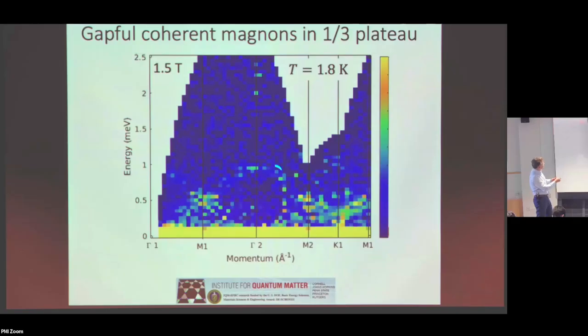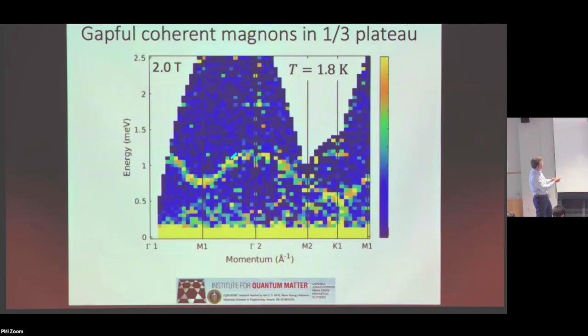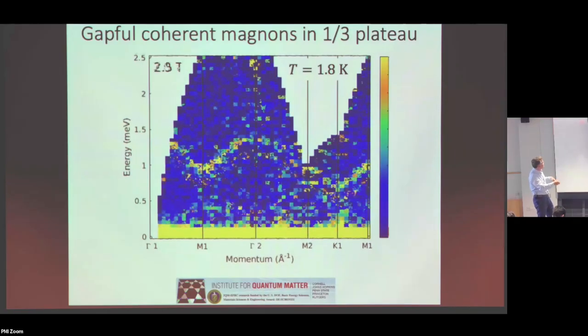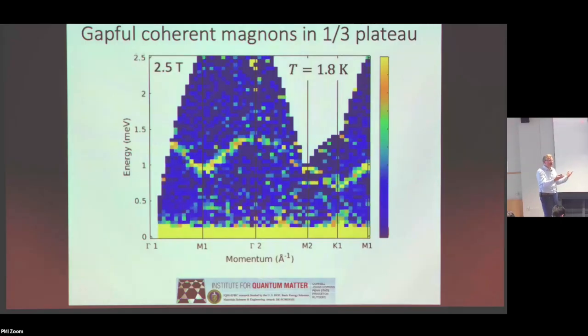And you can see kind of out of this morass, you get this lovely spin wave type mode that kind of appears. And so what's happened is that now I have introduced a gap in the spectrum, and I've converted the system from an entangled state into a product state that has single particle spin flip type excitation. So I really have magnon excitations now once I get into the plateau phase.